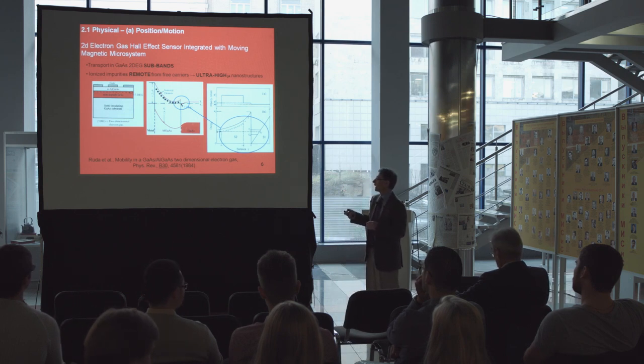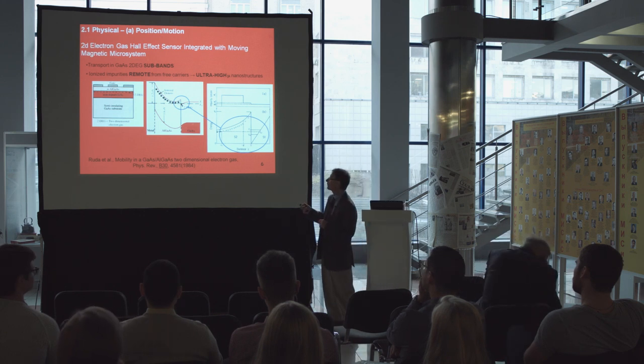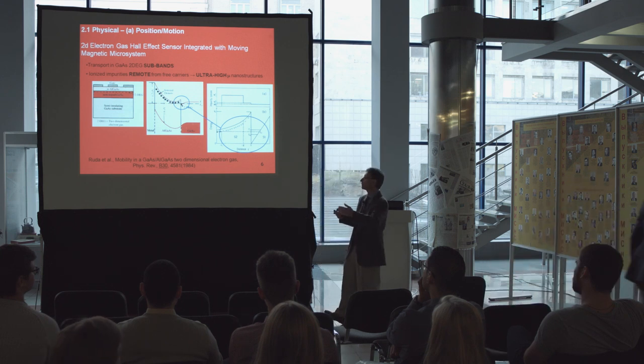into this side, this aluminium gallium arsenide material, a fraction of these donors are ionized at room temperature, which means they give their electrons off. And these electrons see a barrier here. This is the energy structure, increasing energy up here. And they have a barrier, but they can overcome this barrier. So those electrons get taken from this side of the structure to here.